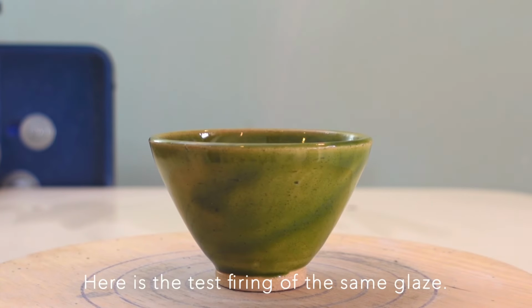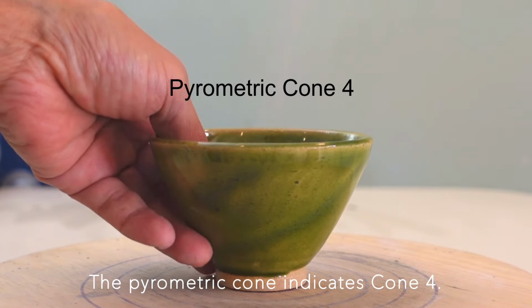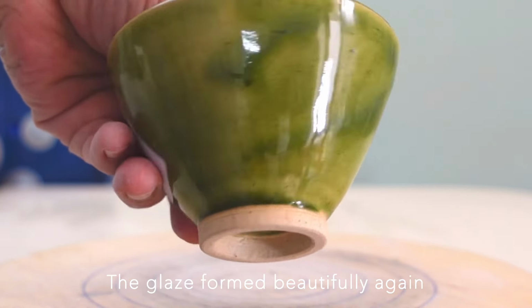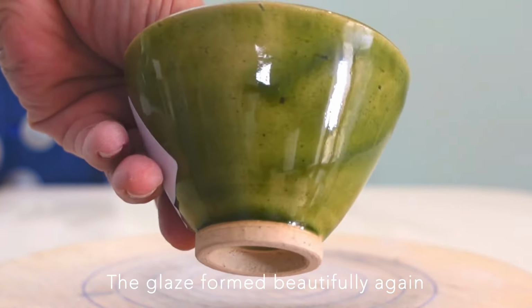Here is a test firing of the same glaze. The pyrometric cone indicates cone 4. The glaze formed beautifully again with a vibrant lime color. This is the same cup I was glazing earlier, and by leaving a thicker area of glaze, I can now assess how long to dip future pieces. The thinner area also has a shiny, translucent lime finish, which means I can use glaze thickness to create variations.